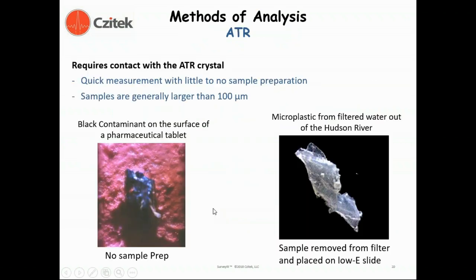Some samples amenable to ATR measurement include: on the left-hand side, a contaminant on the surface of a pharmaceutical observed and selectively measured through the diamond ATR crystal; and on the right-hand side, a microplastic from filtered water from the Hudson River, moved and transferred to a Low-E glass slide and measured in ATR mode. These samples in ATR are generally larger than 100 micrometers in dimension.